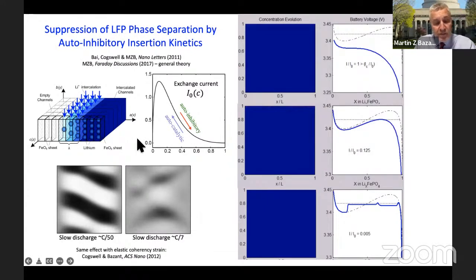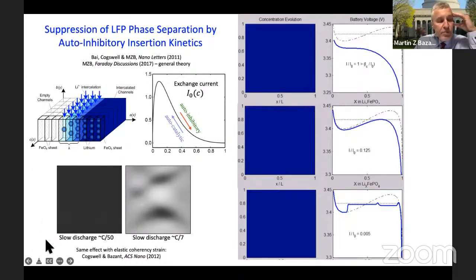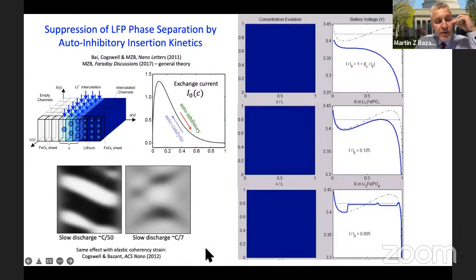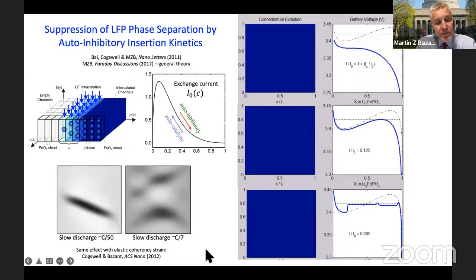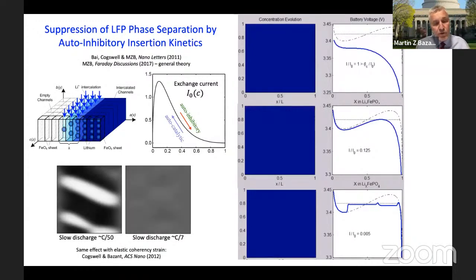Now, I mentioned elastic stresses. And so if you repeat the same calculation that I showed here from a 2012 paper, you can do the same sorts of things where at a slow rate, when you insert in the crystal, looking down on the top facet now, you can see these stripes forming of the different phases. And if you go at a higher rate, those phases are again suppressed, and above a certain critical rate, they disappear.